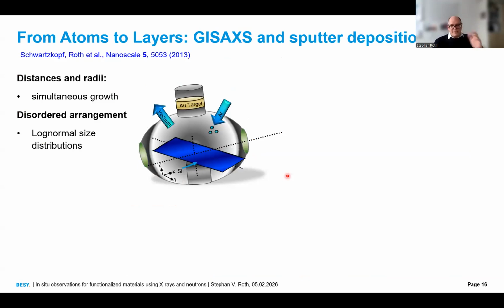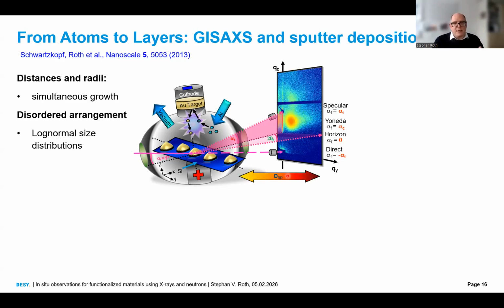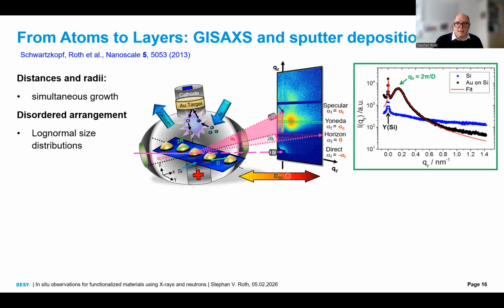And just to remind you, this is how we picture it. We put a very big sputter chamber into the beamline. So sputter chamber, it's a vacuum chamber. We fill argon in, and we ionize the argon. And with this, we kick out target atoms from a target. This can be gold, silver, aluminum. These are the three metals I'm focusing on in my talk. And then these atoms fall on the substrate. They diffuse on the substrate and create nanoclusters. And while these nanoclusters are growing, we observe their growth with grazing incidence small and wide angle X-ray scattering.